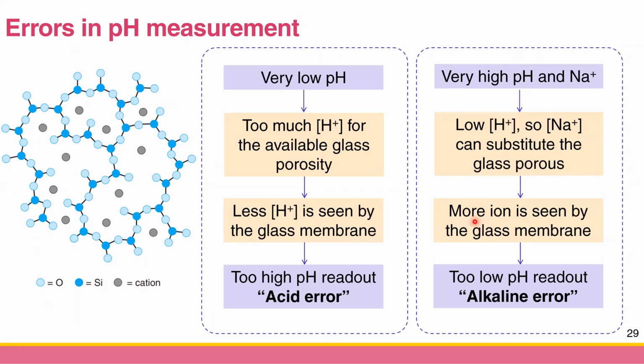So it turns out that more ions can be seen by your glass membrane, and your glass membrane does not know whether that ion is proton or sodium. It's gonna respond the same because the charge is +1, the same. So your pH readout now is gonna be too low. Like if your sample is pH 13, maybe it will give you a value like 12.5, something like that. And we call this alkaline error. It occurs when you have a sample with very high pH and very high sodium concentration. That's the second one.